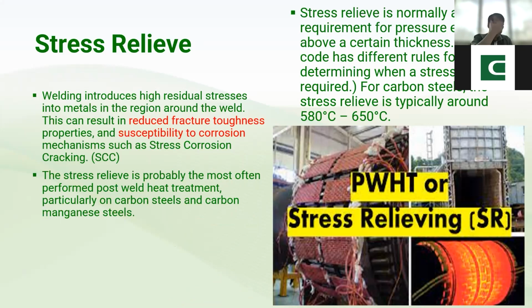Yung isa po kasi, para nasagot na rin po kasi ang nakalagay po dito is yung 1 hour na soaking time, standard po ba yun or depende po sa material? Standard yun sa carbon steel, 1 hour per inch thickness. Pero kapag chromium molybdenum, 2 hours per inch thick. High alloy steel, based on ASME Section 8.